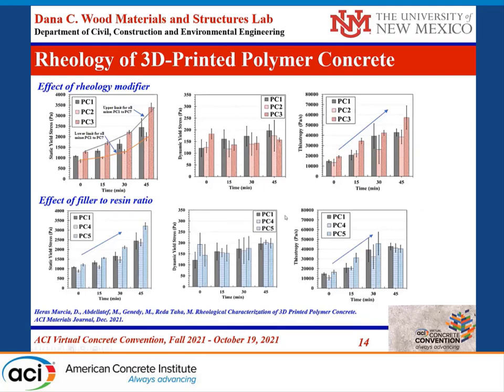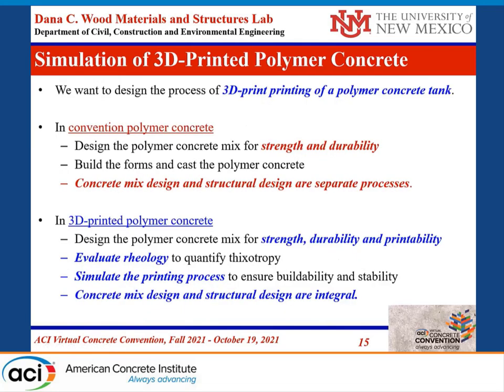The interest of this study is simulation of the 3D printed polymer concrete process to be able to print a 3D printed polymer tank. In conventional polymer concrete, you design the mix for strength and durability, build forms, and cast — with no tie between concrete mix design and structural design. In 3D printed polymer concrete, the mix design needs to address strength, durability, as well as printability, which relates to structuration and buildability.